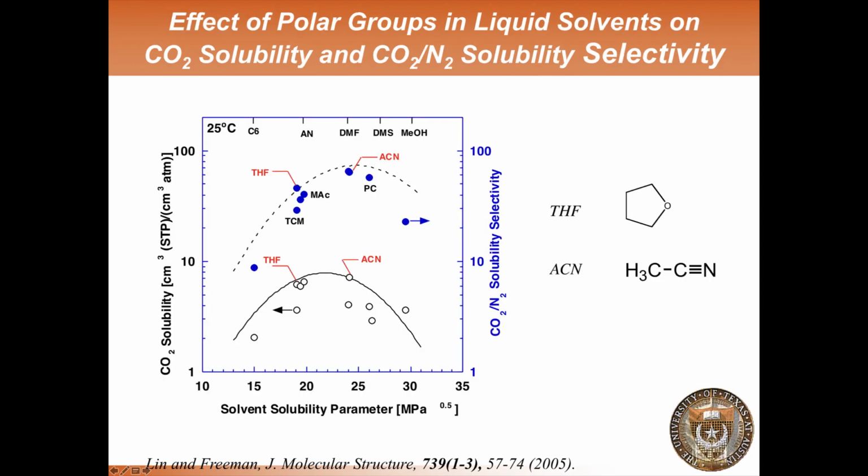The data here is all about CO2 and nitrogen dissolving into a variety of liquids, and this is often where I would start in looking for chemical groups that might make useful additions to polymers to enhance solubility of a given species like CO2, for the simple reason that there's enormously more gas solubility data in liquids than there is gas solubility data in polymers.